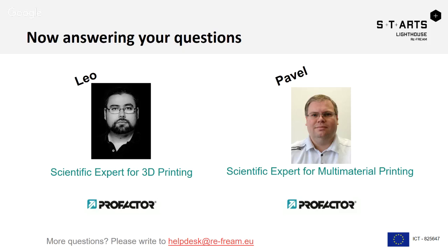And if you want to know how big this viscosity range is, you can look it up on the Stratasys homepage or in some other documentation. It's in the range of 15 to 25 millipascal seconds. That's the key property to know.